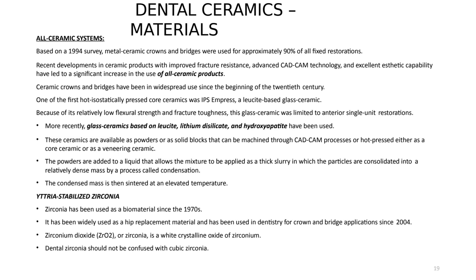These ceramics are available as glass, powders, or solid blocks. For each system, we must use layering porcelain that is compatible with the substructure. If using a leucite-based material, we must use build-up porcelain compatible with leucite — we cannot use lithium disilicate build-up porcelain on leucite glass; they are not interchangeable.